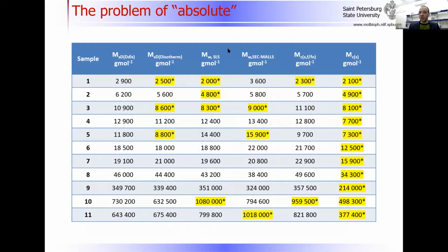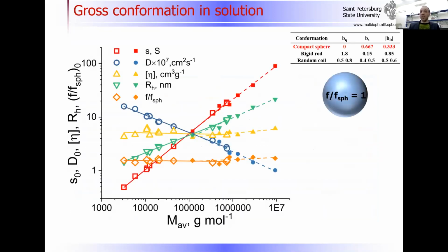And we see that even if you use static light scattering, batch one, still it gives you, for example, for a low molar mass sample, values of that range. The best examples we have from the combination of the sedimentation and diffusion coefficients estimated from the dynamic light scattering. Interesting. Okay, and then when we have the molar mass, I can compare the molar mass in the double logarithmic scale with the sedimentation, diffusion, intrinsic viscosity, or the hydrodynamic size, in the double logarithmic manner, so-called scaling relationships.